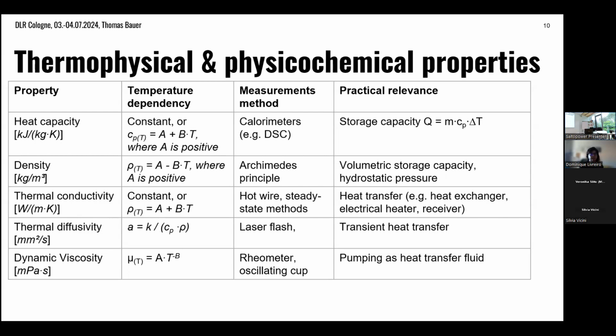Then we have density. We typically see a linear decrease of the density, which means the salt expands once you heat it up. And then we have properties like thermal conductivity, which can be positive or negative with temperature. Thermal diffusivity, we heard this before from Christian, can be important for transient heat transfer phenomena like the moving barrier. And then we have the viscosity with a very strong dependency. High viscosity near the melting point, and then it drops. And the typical correlation is this one.